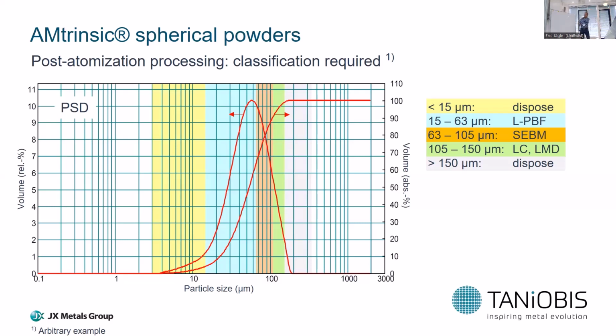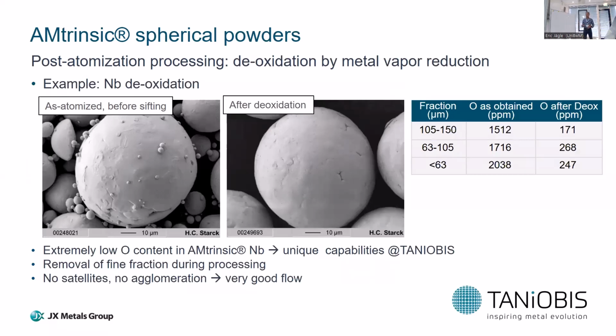The next step, if required, is a deoxidation process. This is a capability which is very unique at Taniobis, which we developed for tantalum capacitor powders, but this can also be applied for a lot of these AM powders, shown here, for example, for niobium. You see two pictures here. This is the powder as obtained after atomization, and this is the powder after deoxidation.